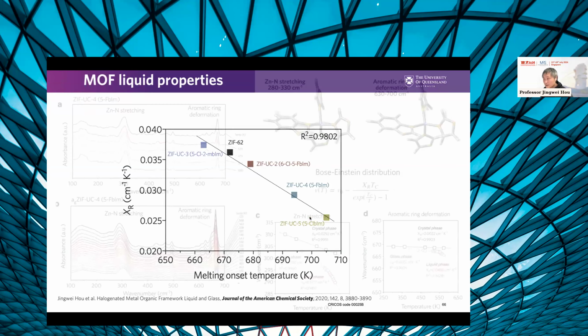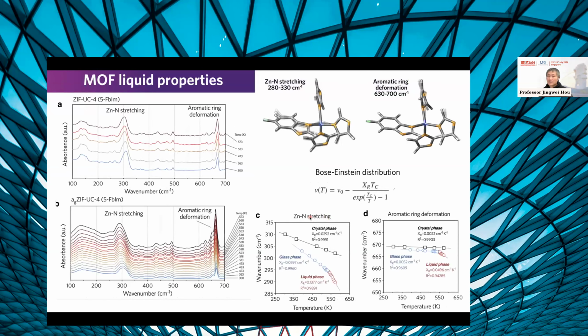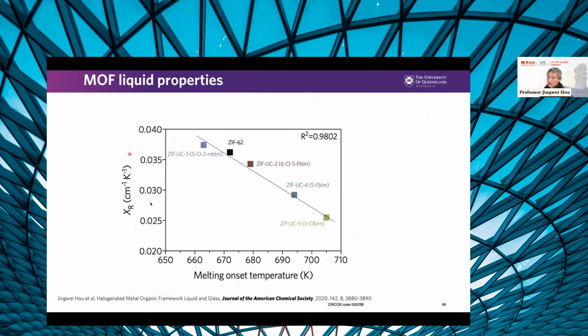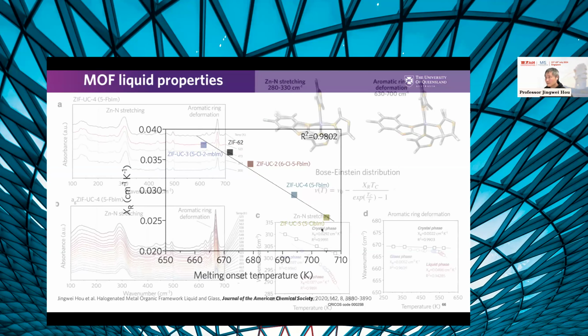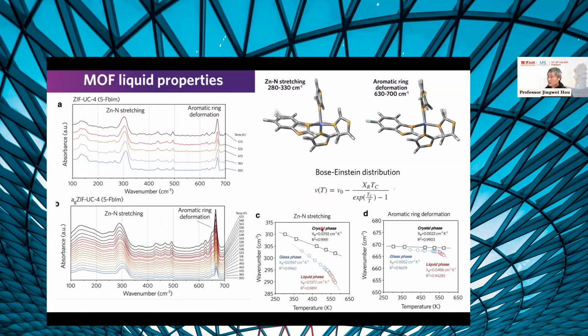That's quite a lot. So some of the melting temperatures very comfortably give us access to study their melting mechanism by using synchrotron terahertz spectroscopy. We can track the peak positions against different temperatures, and after fitting with the Bose-Einstein distribution, the peak position fits the distribution very nicely. Different forms follow different slopes and different coefficients, and the coefficient agrees very well with the melting temperature of the framework. So we can very comfortably say the melting mechanism is really the stretching and deformation vibration of a few ligands and coordination bonds within the framework.